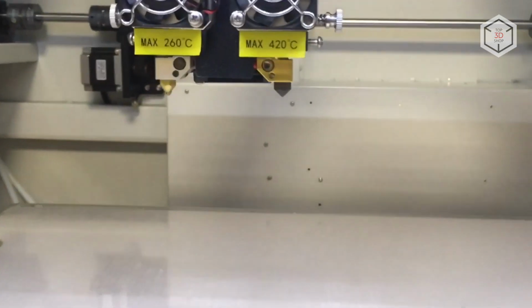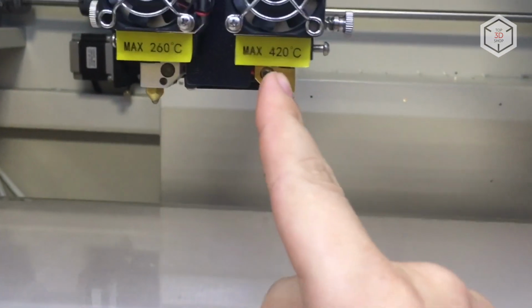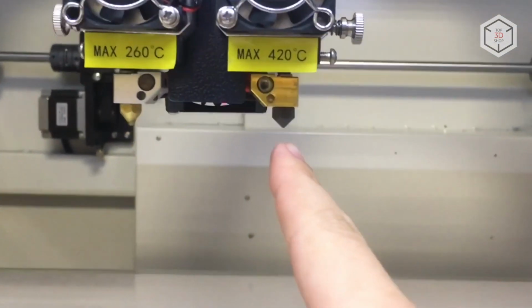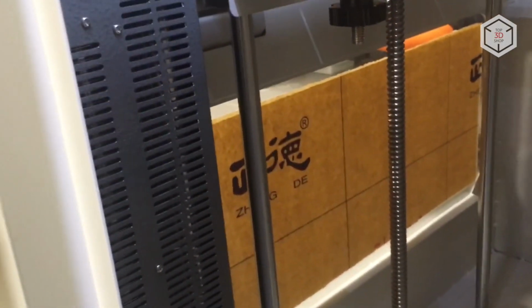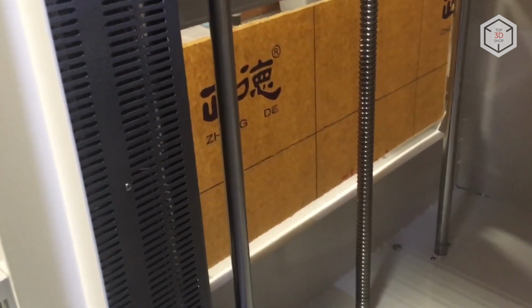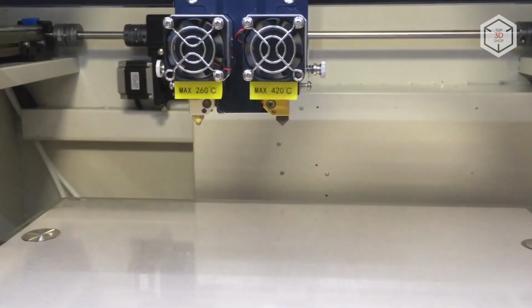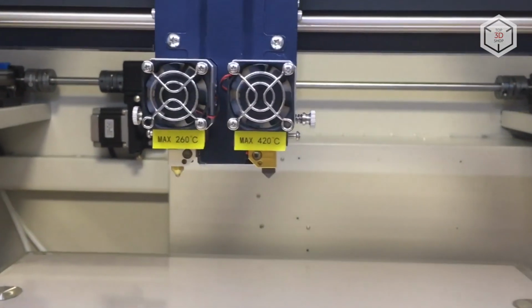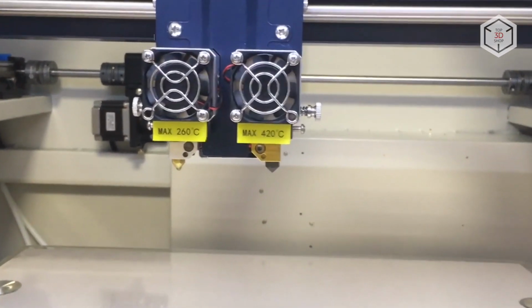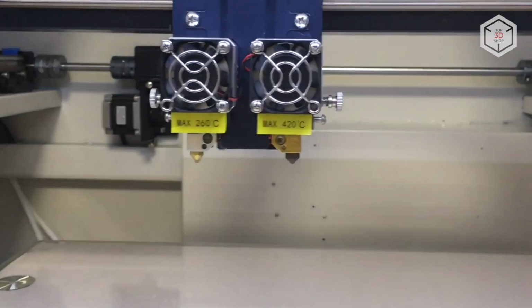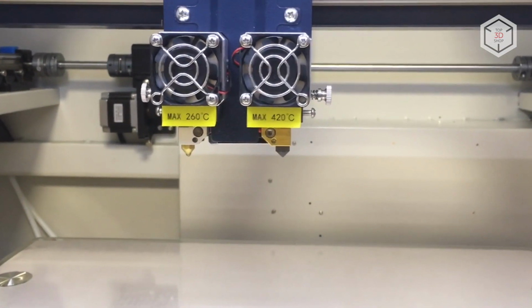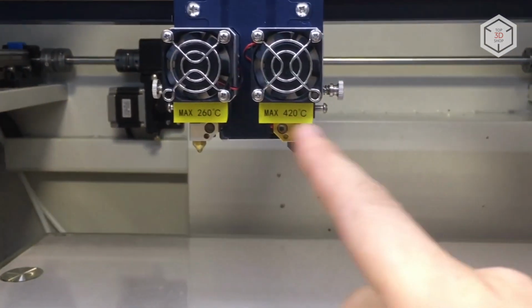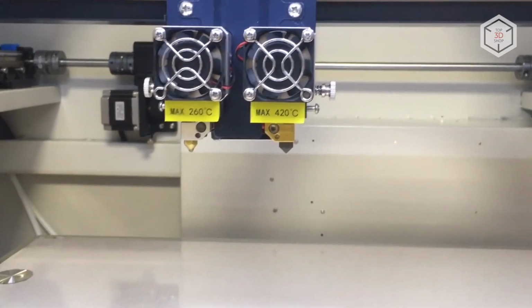The right extruder has a hot end with a maximum operating temperature of 420 degrees and a carbon steel nozzle. The heating system is installed on the left, behind the grill, to ensure high temperatures inside the chamber. PEEK and other high temperature plastics are demanding in terms of temperature control. We will heat up the extruder, chamber, and bed to the required temperature and feed the plastic. An important point: before using the PEEK filament, you need to make sure that there is no plastic left in the hot end from past sessions. Otherwise, ABS or PLA residue can literally boil at about 400 degrees, requiring thorough cleaning of the clogged nozzle.